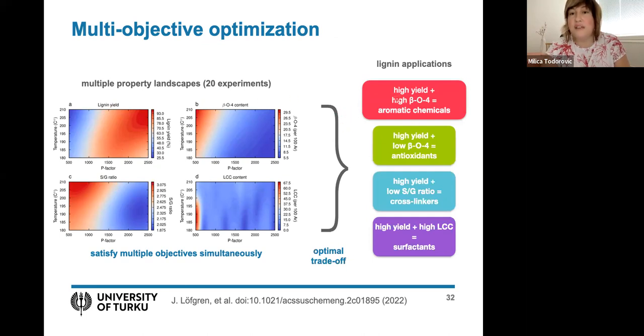Here you see four different properties. So here's the lignin yield and beta O4 you've seen before. They were also interested in chemistry of this SG ratio units and LCC content. And we were considering how to put this together. I mean, mostly you always want lignin yield if you want to produce lignin for some applications. So if you target high yield and high beta O4, this lignin that's produced can be used as feedstock for aromatic chemicals. You can also look at high yield and low beta O4, which is kind of here is the optimal solution. This is ideal feedstock for antioxidants. So you can use lignin for antioxidants.